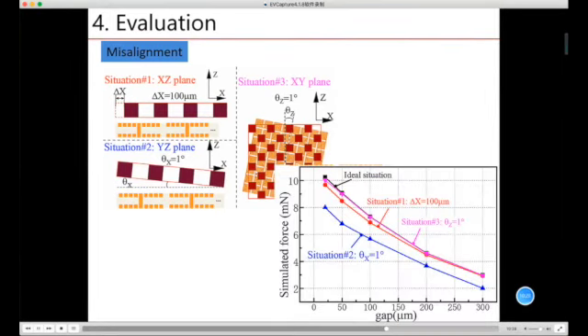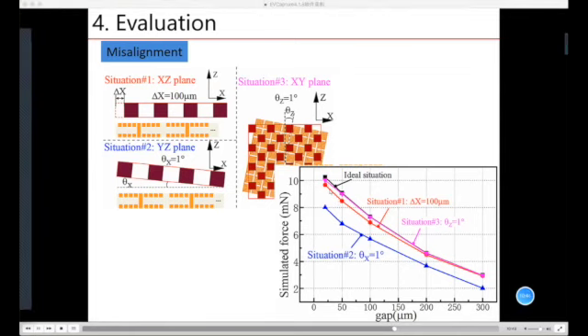And then we simulate the performance of the magnetic force. We can see that for the ideal simulation, situation 3 has degraded little, and situation 1, the translational direction, has decreased the performance to around 10%. And for situation 2, the X directional rotational misalignment degrades the performance to around 20%. And in real actuation situations, it is a combination of different misalignments, so that it caused the degradation of the generated electromagnetic force.